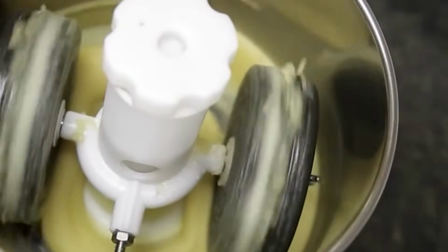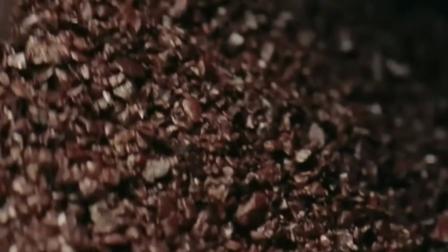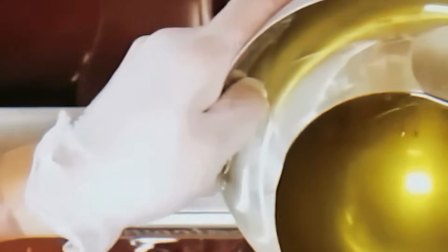Each ingredient is dosed using gravimetric feeders and poured into large, high-speed mixers where they are combined into a smooth, uniform brown paste. This initial chocolate mass is far too coarse to be palatable, so it is sent to the refining system. This consists of a 5-roll mill where the mixture passes between sets of rollers that progressively reduce the particle size down to below 20 microns, creating a texture that feels smooth and creamy on the tongue.